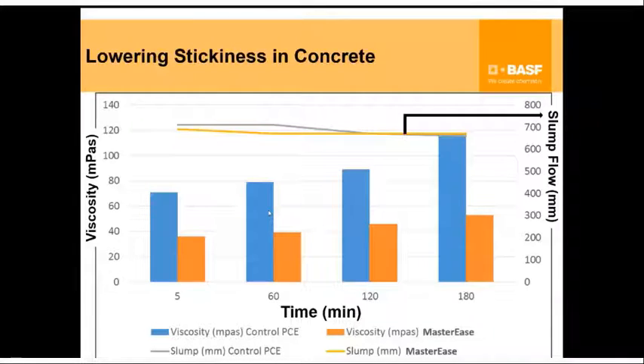However, with this new type of rheology enhancing admixture, the increase is minimized. So two things happen. At 5 minutes, you see a drastic reduction in viscosity with these materials, but even over time, the viscosity doesn't change very much. So why is this important? The reason it is important is because while we do all the SCC testing at 5 minutes, we are not placing the concrete or pouring the concrete or pumping the concrete at 5 minutes. We are doing it at 60 or 120 minutes, which means that if we get a nice number at 5 minutes, that doesn't mean that it's going to pump very well at 3 hours.